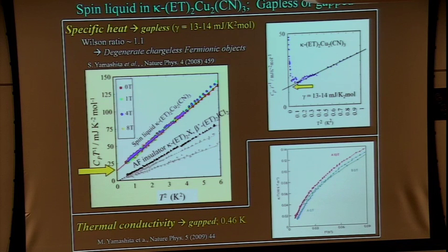Yes. So how do you understand the field dependence? The specific heat does not show any field dependence up to 8 Tesla. They maybe reported some field dependence at higher temperatures, so they speculated about some contribution from the phonons or something like this, but I'm not sure. At high temperatures, this is sample dependence. No, sorry, you're asking about this field dependence? I don't know. The data at 0 Tesla, and then this kappa over T is a little bit enhanced there. But in specific heat, there is no field dependence.